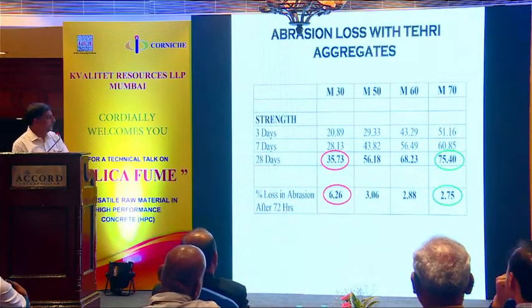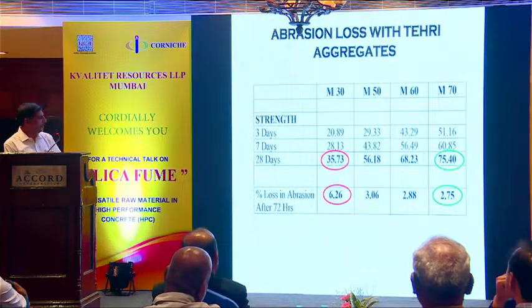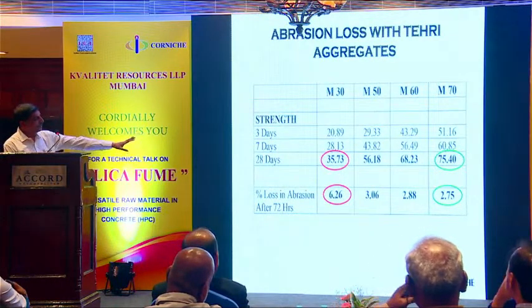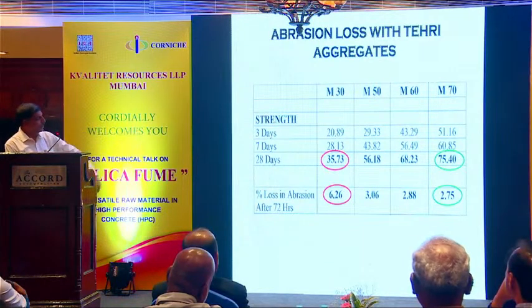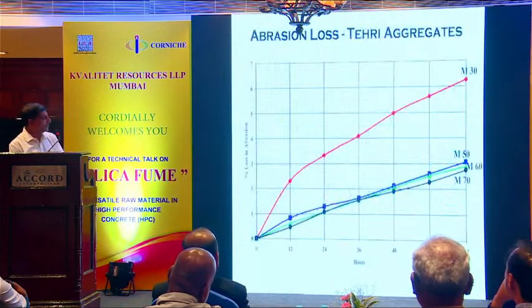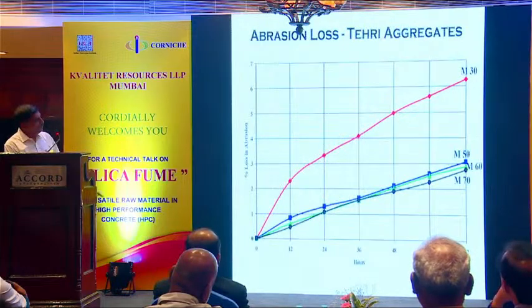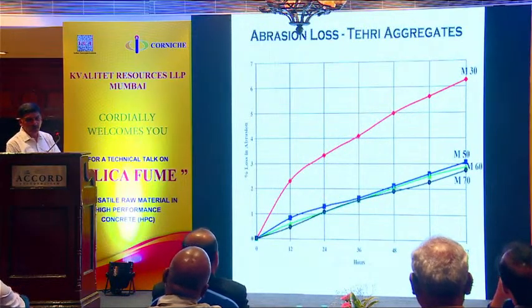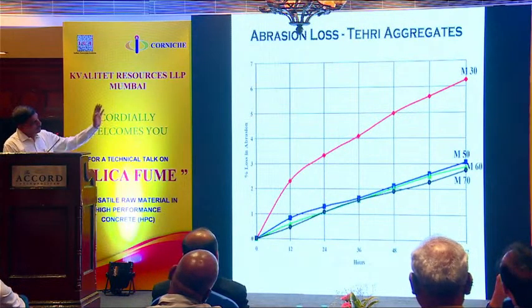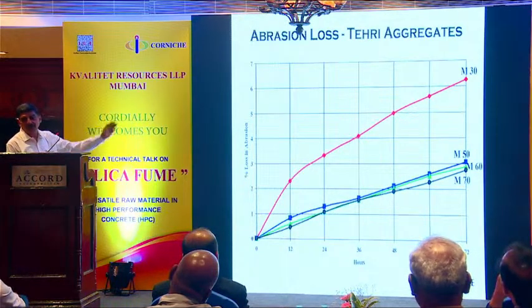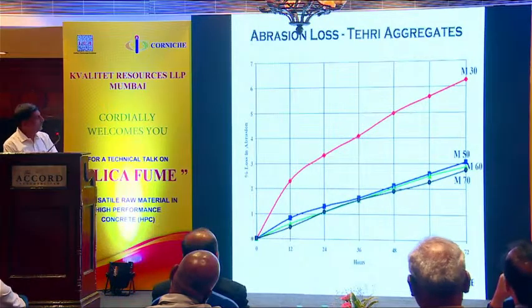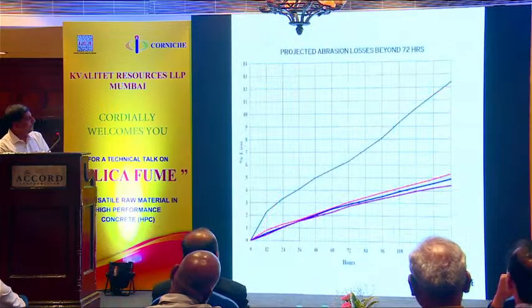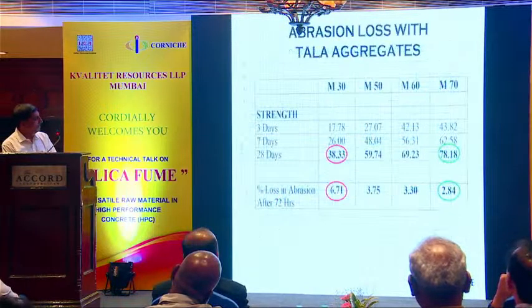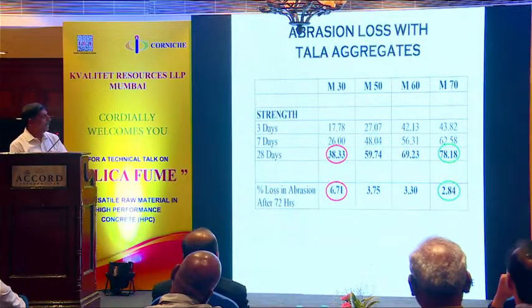Abrasion losses, you can see. The numbers with silica fume concrete are coming down. I'll show the condition of the samples. When we went beyond 72 hours to run this, the conventional concrete started giving away completely. Silica fume concrete was flat, no abrasion. Same with Tala.